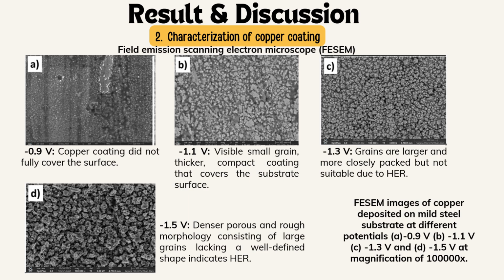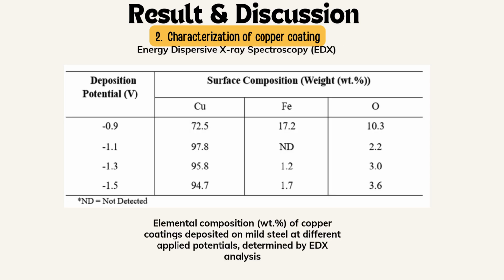For the characterization of copper coating on mild steel, firstly is the FESEM analysis. At negative 1.1 volt, small grain sizes were visible, indicating nucleation and growth of copper atoms, which result in a thicker and compact coating. Next is the EDX analysis. A high amount of copper content with 97.8 weight percentage was detected at deposition potential of negative 1.1 volt with absence of iron element, suggesting that the mild steel substrate was fully covered with copper.